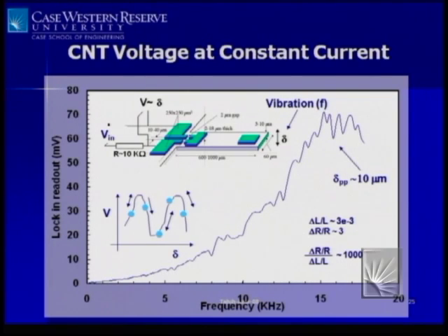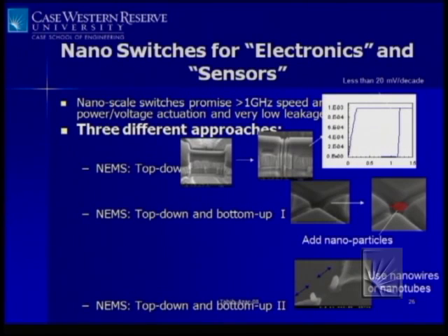So this enables you to come up with a piezoresistive sensor that's very small, can be readily grown inexpensively, and doesn't have the problems of scaled piezoresistors in silicon. If you take silicon piezoresistors and make them smaller and smaller, as the volume becomes smaller, the statistical fluctuation in doping concentration makes their characteristics vary dramatically from one device to another. But carbon nanotubes are all the same, more or less. Although they are very small, because of their structure there is not much statistical variation.